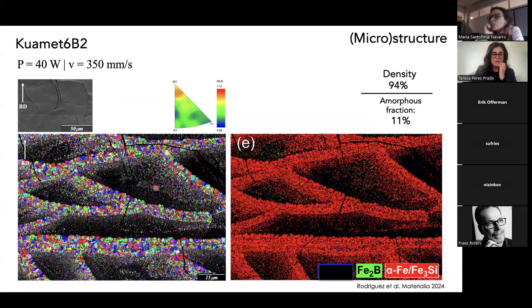Let us zoom a bit more into this microstructure. We used EBSD to look at these heat-affected zones, and this is an inverse pole figure map showing the orientation along the build direction. Grains are equiaxed and randomly oriented. The maximum sizes, in the vicinity of the melt pool, are around a couple of microns, and then they decrease in size as we go farther away from the bottom of the melt pools.